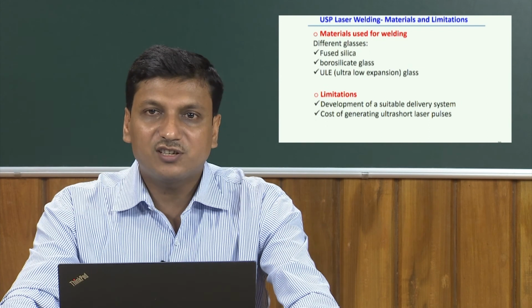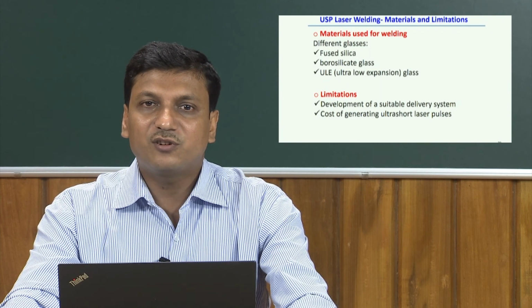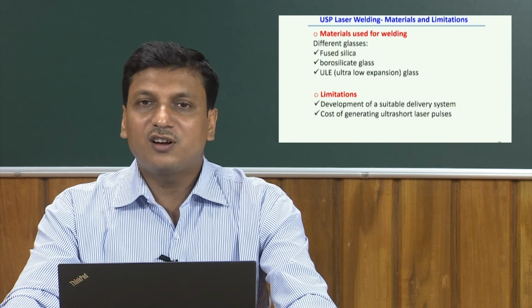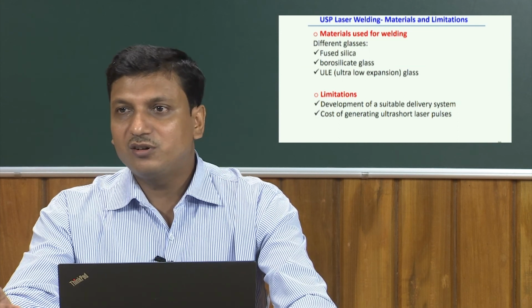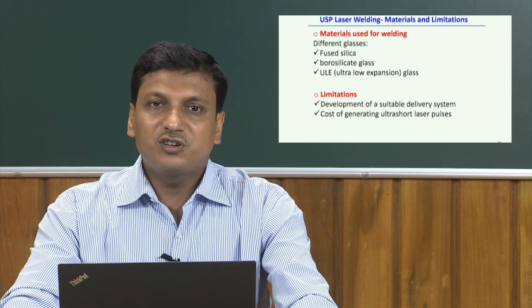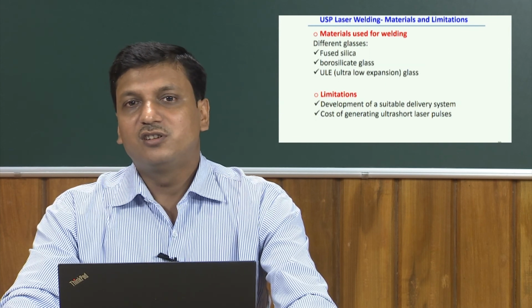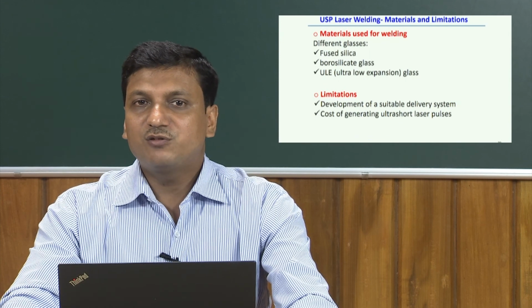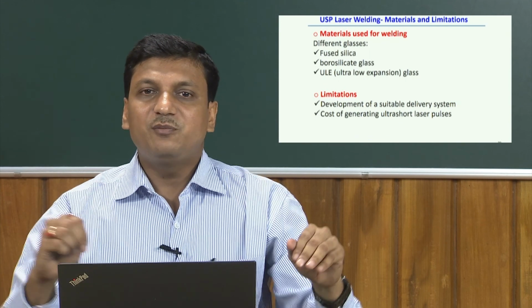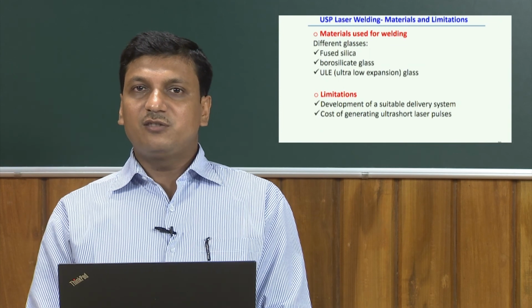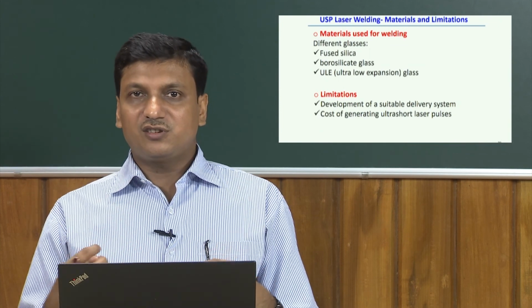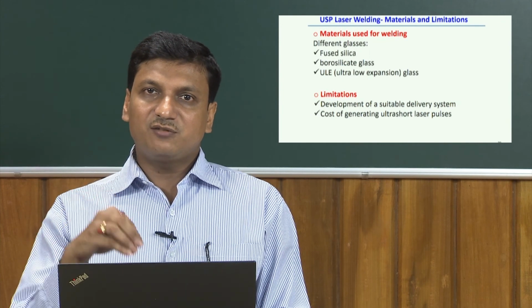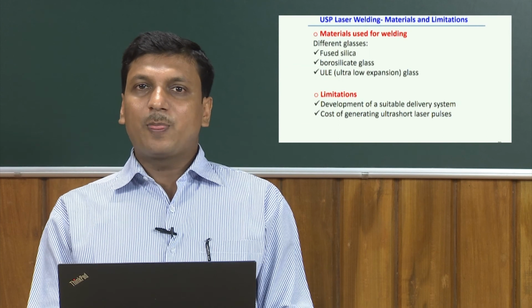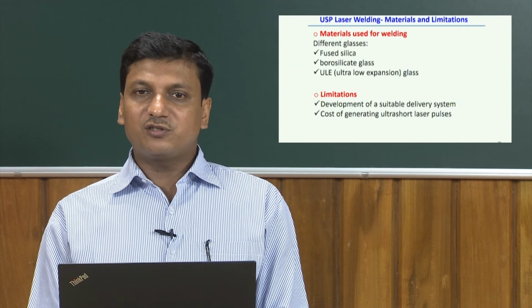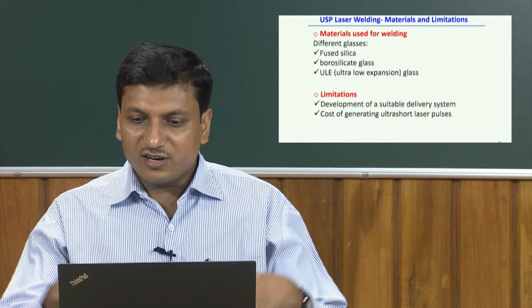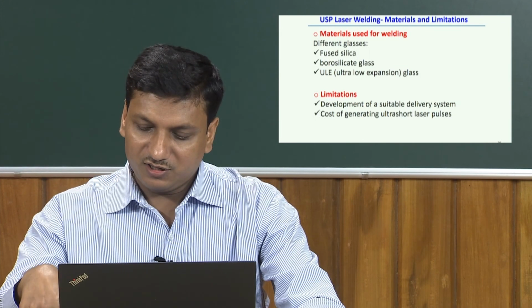So, we can find the typical application and limitation of the ultrashort pulse laser welding process. Materials using different types of glass, so far we observed, by the application of the ultrashort pulse laser. Fused silica, borosilicate glass and ultra low expansion glass are the typical materials mainly used for the ultrashort welding process. But the limitation is the development of a suitable delivery system, that means the design of jigs and fixtures, and the focusing of the laser in a very defined zone, which is the main limitation of this process. And definitely cost is another important criterion for the wide application of this welding process.